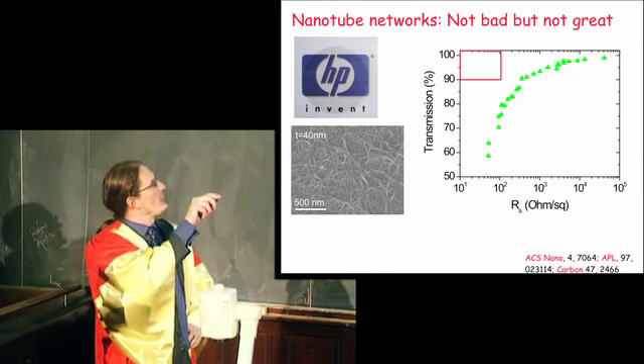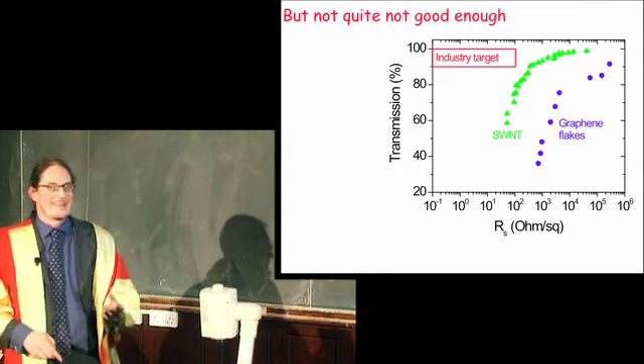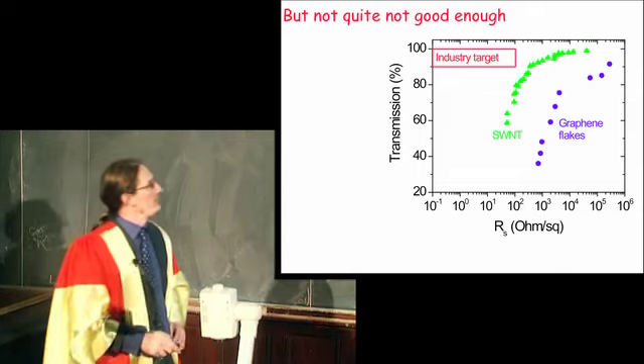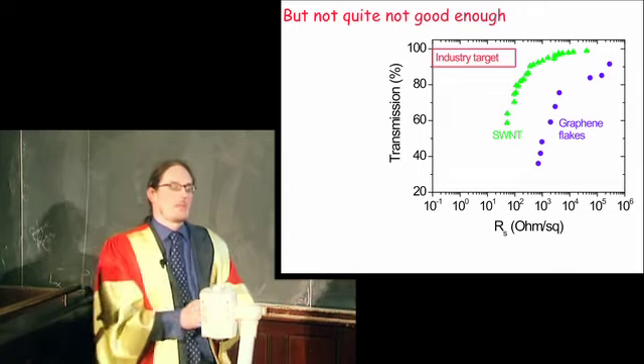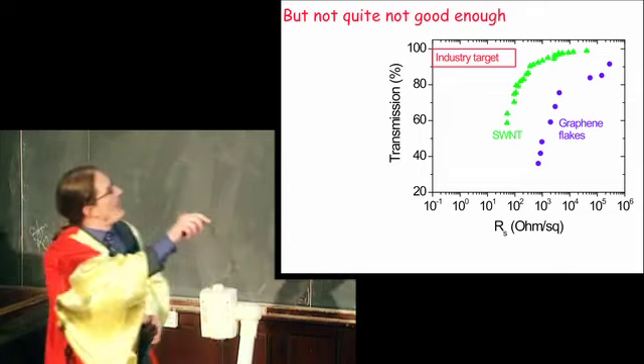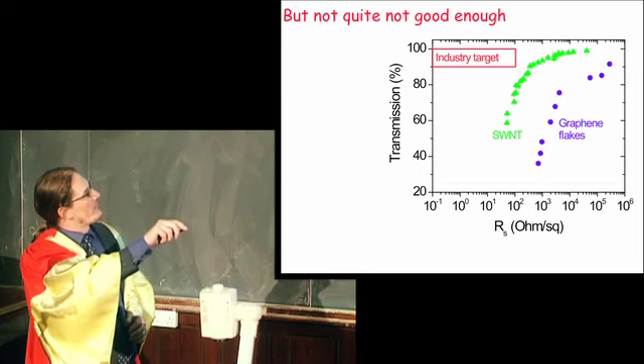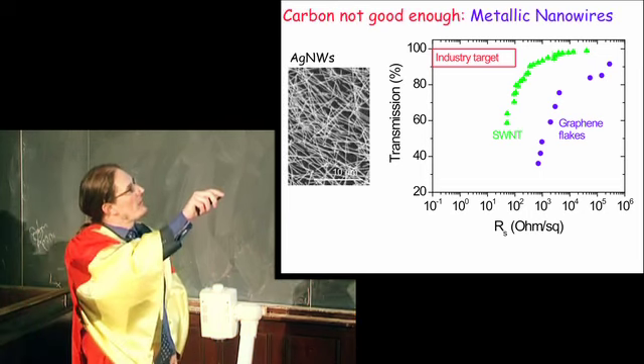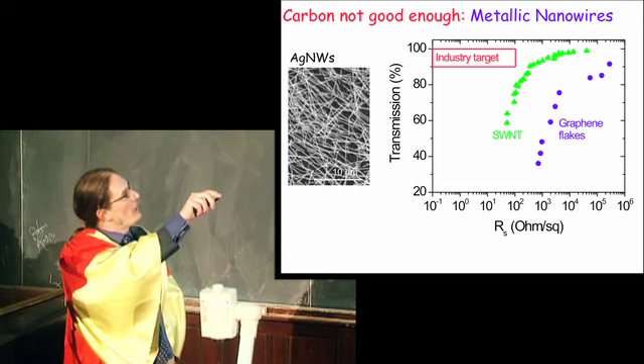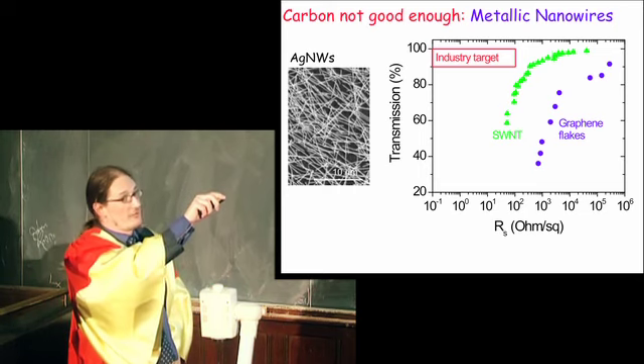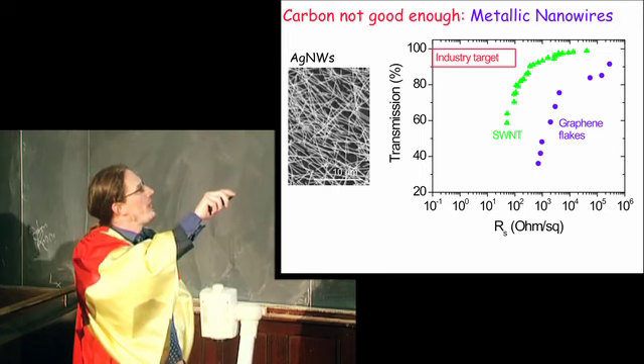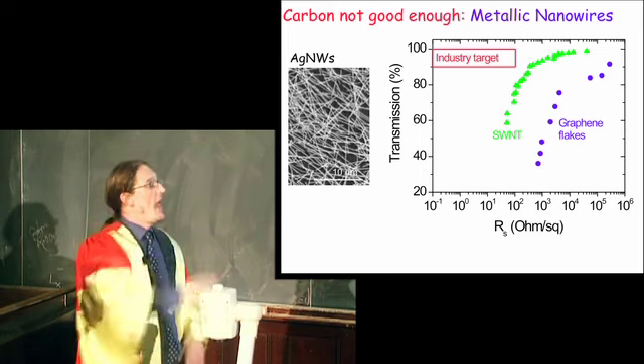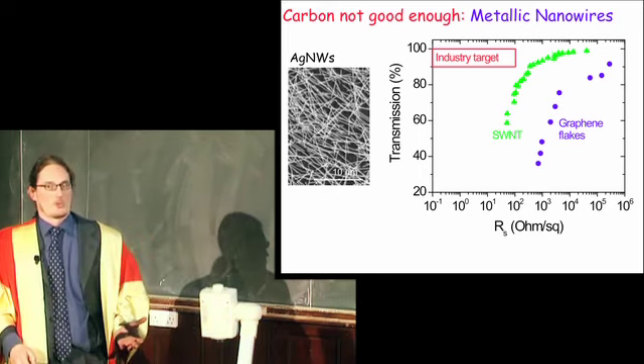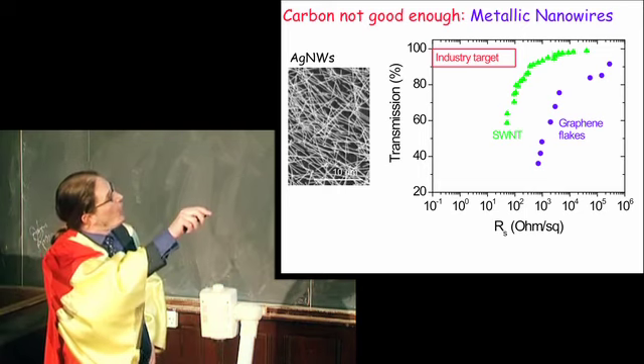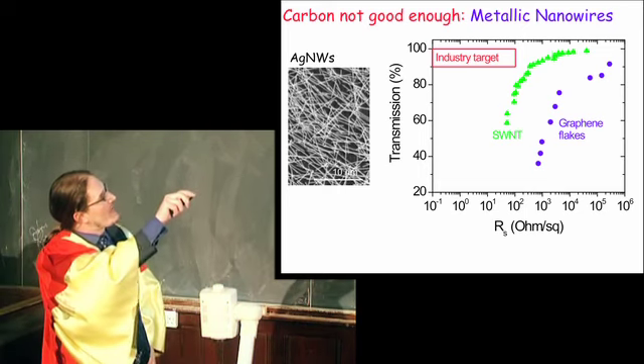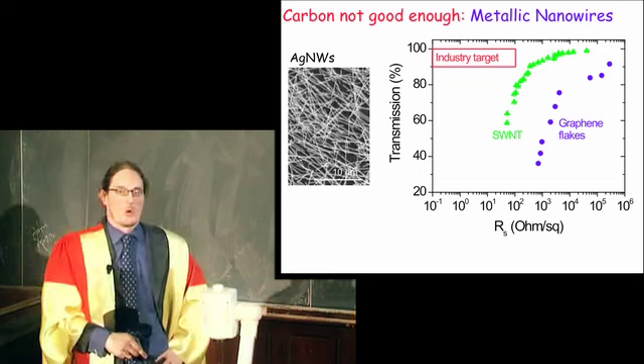Now, what if we measure the optical transmittance of that film and the electrical resistance? Well, what you do is you make films with a range of thicknesses and measure transmittance and the resistance. The problem is that thin films have high optical transmission but high sheet resistance, which is not what you want. Thick films have low transmission and low resistance, which is not what you want. And in fact, there is no thickness that gives you a combination in this box, which defines the industry requirements.